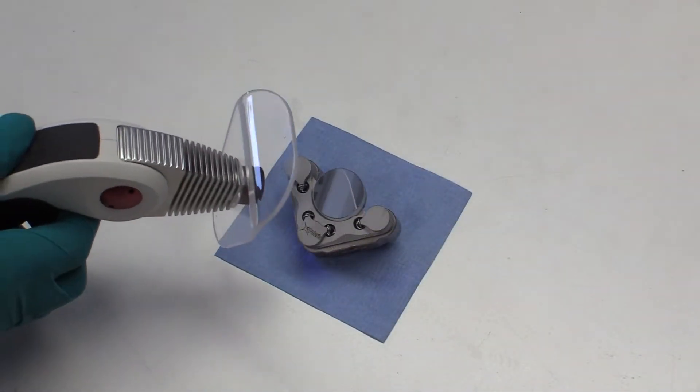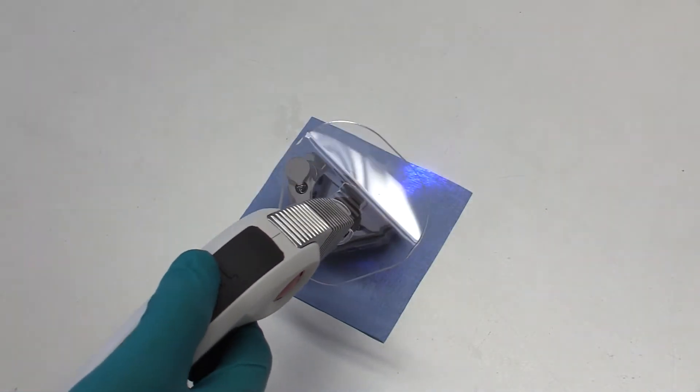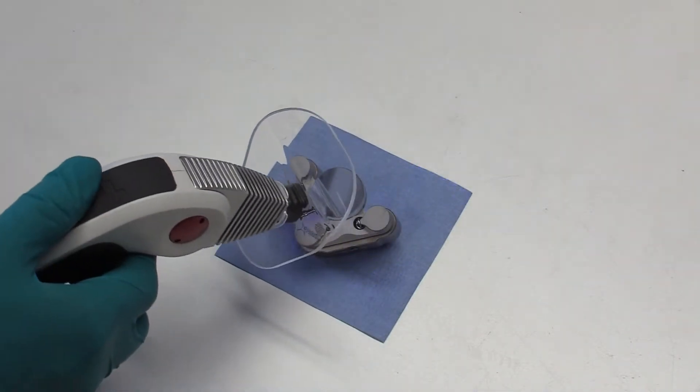Use the UV LED system to begin curing the optical adhesive. The initial cure should consist of one minute of UV exposure around the entire glue plane.